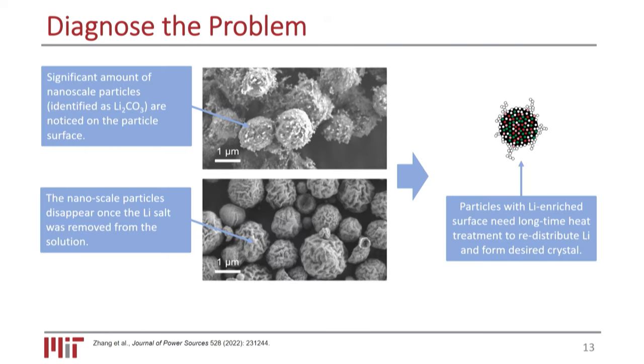So we thought, why couldn't we do this via the traditional method? And so we created this baseline. We used our method to generate NCM811 particles, and we found that we need to calcinate it at 750 Celsius for 13 hours.